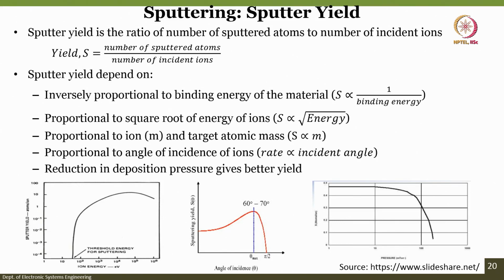So, you can see sputter yield versus ion energy. As you keep on increasing energy, at a certain point the yield increases, then it reaches saturation and then starts degrading. Generally, the angle of incidence is between 60 and 70 degrees for sputtering yield. While for pressure versus sputtering yield, if you see, at a lower pressure the sputtering yield is better. As you increase the pressure, the sputtering yield comes down, right.